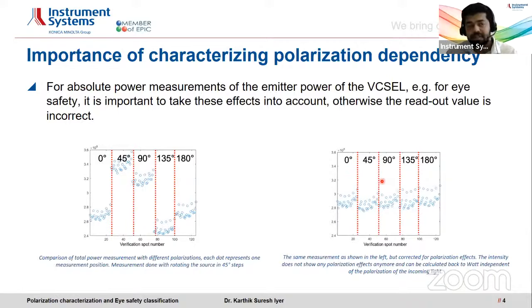Once we do such a polarization correction, as you can see here on the right side, it's the same measurement that we did on the left side, except that now the polarization correction has been applied. The polarization effects of VCSELs, which are pretty much inherent for typical VCSELs, are corrected for. Here you can see that the intensity does not show any polarization effects anymore. And you can calculate these values back to watts, so the power, independent of the polarization of the light coming from the VCSELs. As I mentioned, these are really important corrections that must be done to ensure really good absolute power measurements for laser eye safety calculations, for example.